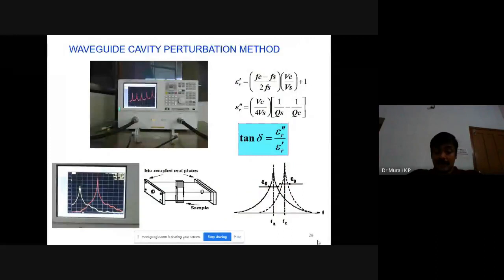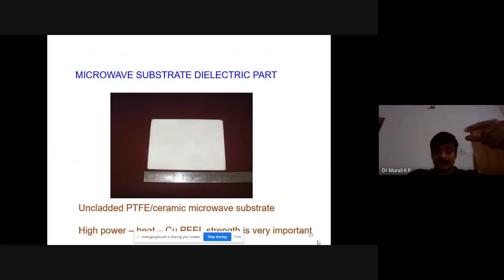For each band there are different waveguides available, like S, X, etc. If it is connected with the VNA or a network analyzer, it will have its own resonance modes. When you insert our sample, that resonance mode will shift, and that shift in frequency and the dielectric constant are related. From that we calculate the dielectric constant of the material, and from the width of the peak we get the loss. And this is a microwave dielectric substrate.